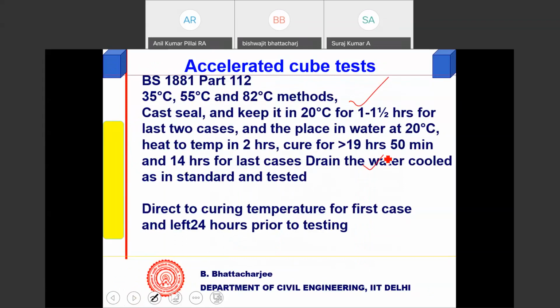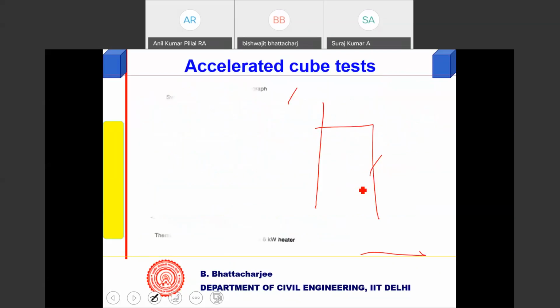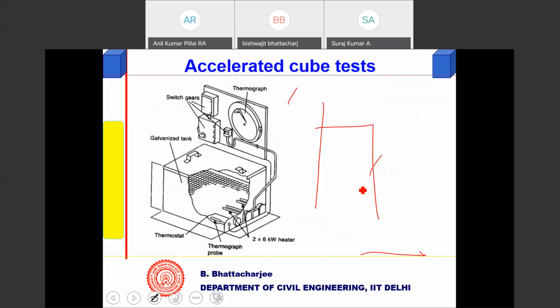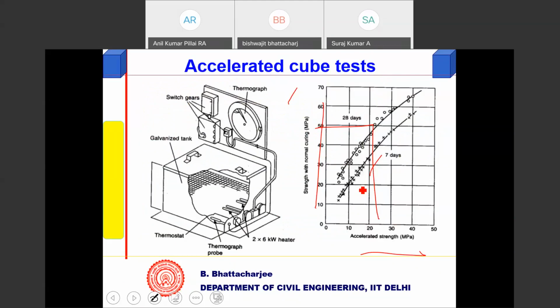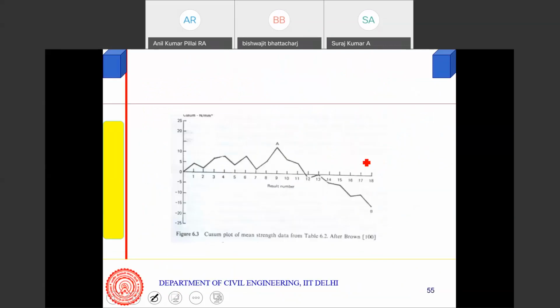So you can choose any one of them from any code, or you can develop your own correlation yourself. The time frame is also given: cast, seal, keep it at 20 degrees for 1.5 hours, place in water at 20 degrees, heat at a temperature, etc. So there's an accelerated test regime, right? So you can do the accelerated test, then you get the answer pretty fast. Then you can verify this correlation later on. If it is changing, then you have to recalculate your data. But this is all possible.